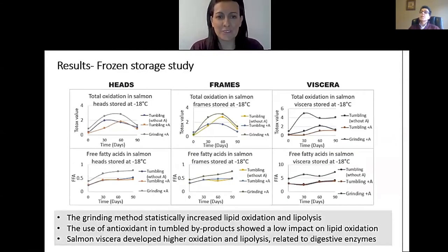During the frozen storage, the grinding method statistically affected the lipid oxidation, while the use of an antioxidant showed a low impact when added to tumbled byproducts and a higher impact when compared to ground byproducts. From the three byproducts, viscera developed the highest oxidation. This was related to the release of free fatty acids catalyzed by the digestive enzymes.